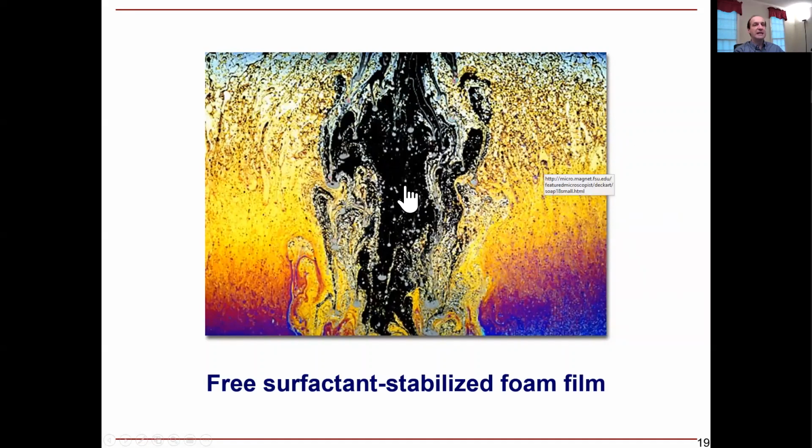This is a foam film, and it is a very thin film, very thin here. It is so thin that you do not have reflectance because practically all the light goes through. Here you have this colored film because the yellow light is where you have the condition for doubling, that is the bright occurrence here. So this is positive interference, this is negative interference, and the color here changes because this is a foam film in gravitational conditions, so you can see the thickness change.